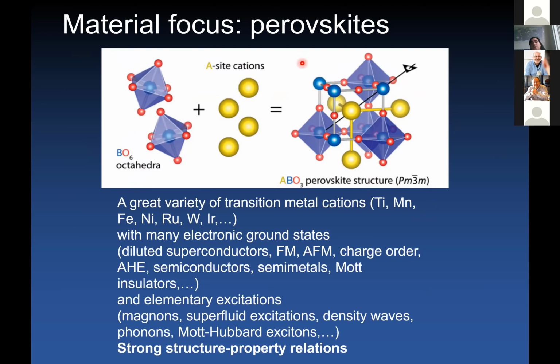The beauty of this perovskite structure is that it allows you to incorporate a great variety of transition metals. And depending on the transition metals that you incorporate, you can find a broad spectrum of electronic states. Just in our lab, we study things from diluted superconductors to various magnetic systems to Mott insulators by changing the type of transition metal cations that you incorporate in the structure. Associated with these ground states, you find very elementary excitations that are exciting to study. And everything is tied together by strong structure-property relations.